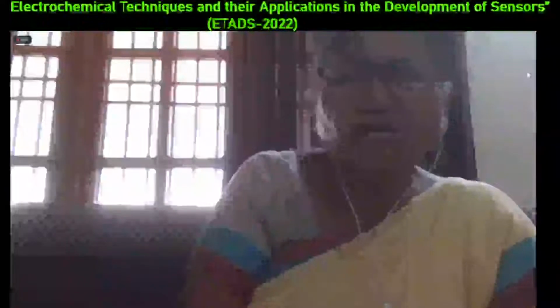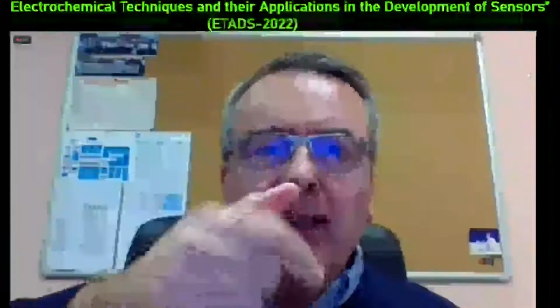The second part is that when you oxidize one ferrocene into ferrocenium, you have the formation of a cation, and you need an anion from the solution to diffuse inside to compensate the charge. So you have both kinetic limitations. One is the kinetics of the electron transfer between the ferrocene groups, and the other is the kinetics associated with the diffusion of the anion inside the material. And depending on the relative density of the ferrocene groups, you can shift from one limitation to the other.